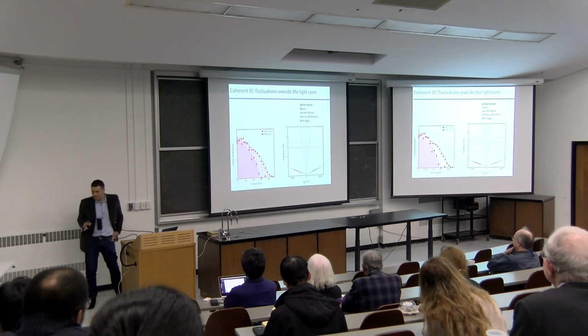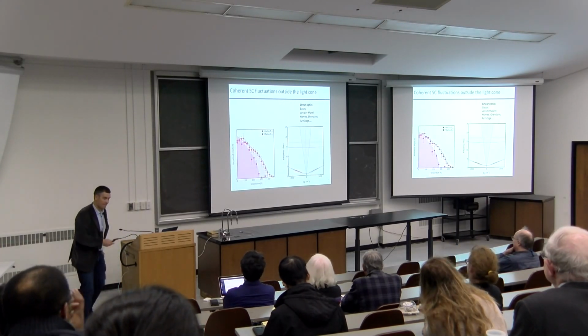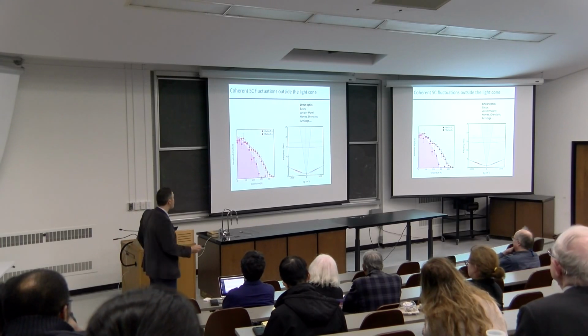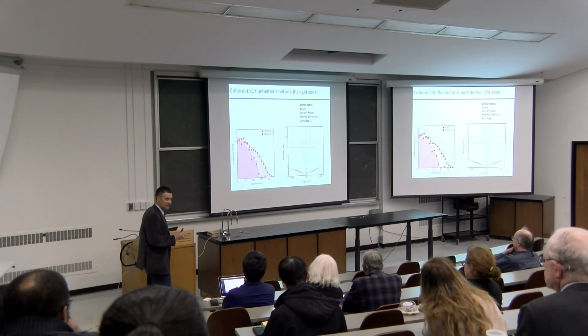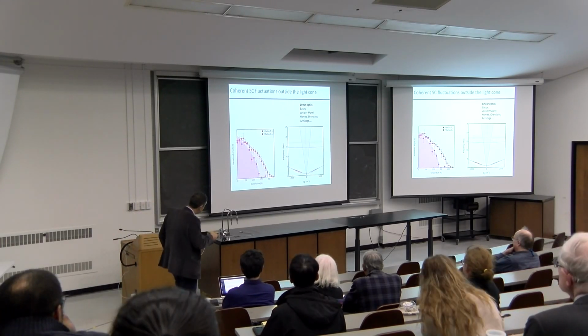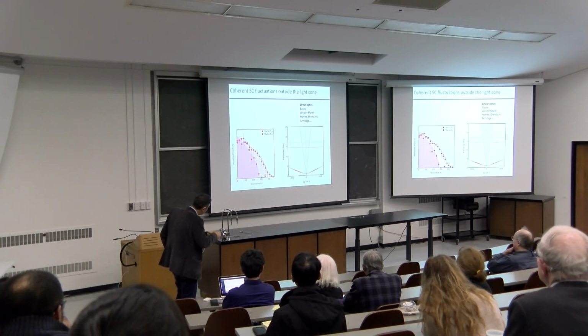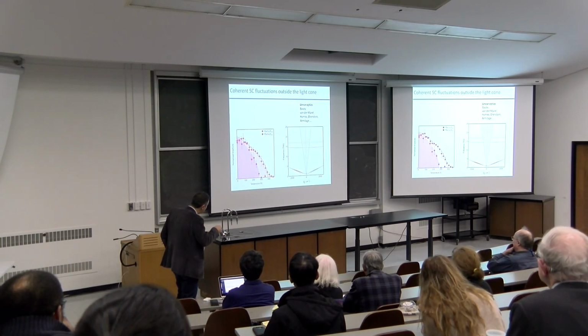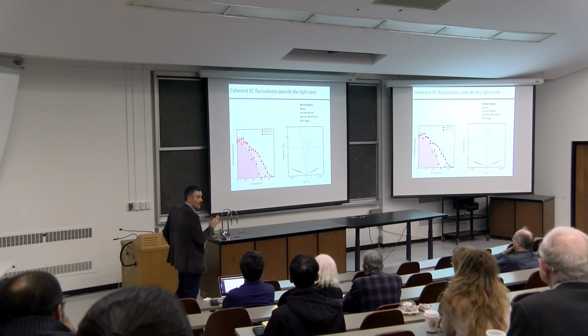Okay, why didn't people see this before? So there's been 100 people who have measured these plasmons as a function of temperature, but the way they measure this is using linear optics. So in linear optics, you're only sensitive to pairs of frequency and momenta which are within this cone, the so-called light cone.